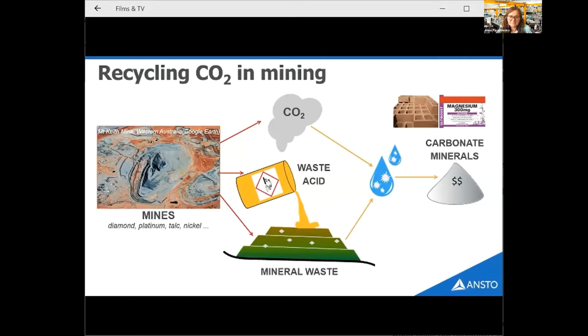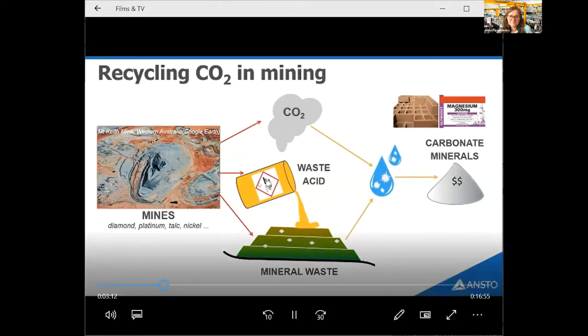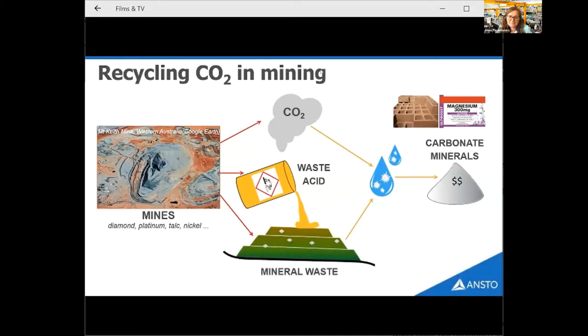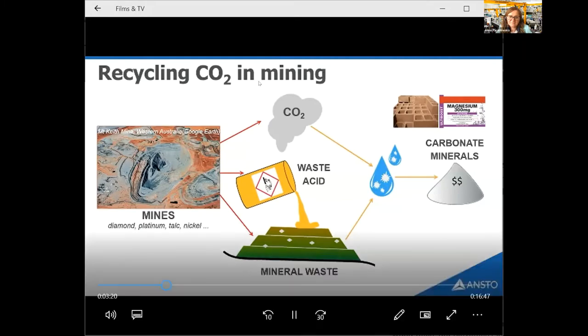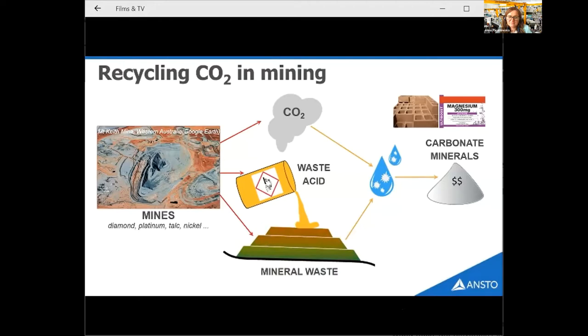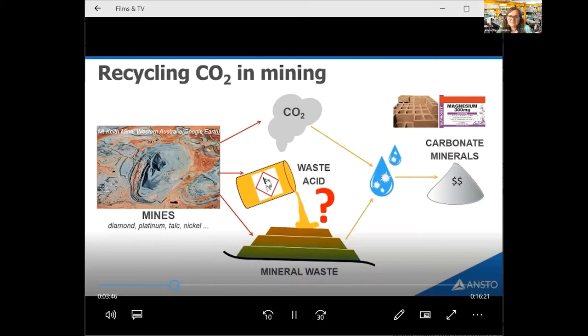But there are some big questions in this system, particularly around trace metals. And tailings in particular contain quite a lot of metals that were either not the target or a result of low recovery grades. That mean even up to 30% of the target metals can end up in the waste. And this is where the synchrotron comes in. So the first question is, what is environmental risk of accelerating mineral carbonation reactions and mineral dissolution? If these rocks contain chromium, for example, if that's oxidized, it's carcinogenic and it's really mobile. It's a mess. So we need to really get a handle on this before we get too ahead of ourselves.